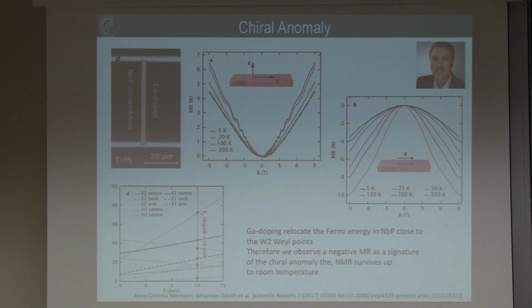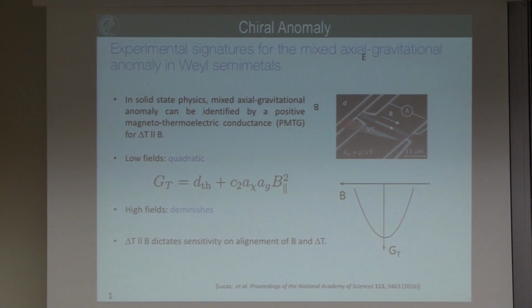So this is what you expect for the chiral anomaly. With this he was even more motivated, because there was a paper published from Subir Sachdev's group, and some astrophysicists became very active in the field of Weyl semimetals, because there was a prediction that if you measure the magnetothermoelectric conductance in this material, you should see certain features related to something people hadn't so far seen in astrophysics, a mixed axial gravitational anomaly.